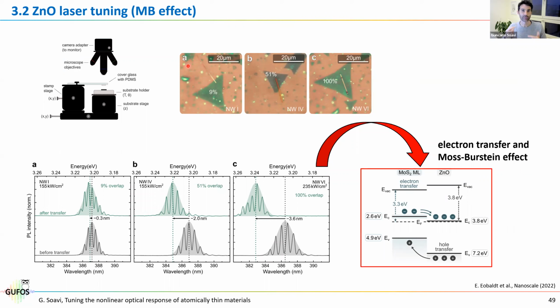One of the ideas was using this lasing to collect PL from the TMD, but this we failed. So even though we see the lasing, we could not detect any signal from the TMD. So we cannot pump the TMD. Probably the power is too low or the coupling is weak. I don't know.